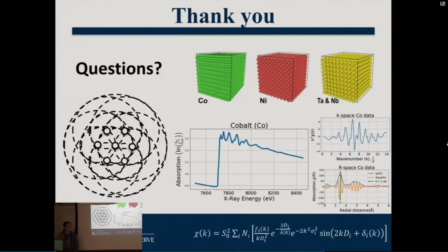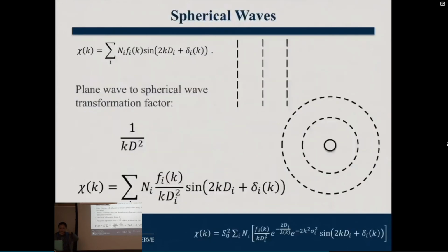I got a little bit lost because it looks like you're trying to get the properties of crystal structure, while later you told us that you're working with glasses. Yeah, so this equation works with any type of material, any structural material, which is actually why we're using XAFS instead of more conventional X-ray diffraction techniques, which could only measure the distance between certain planes in a crystalline structure.